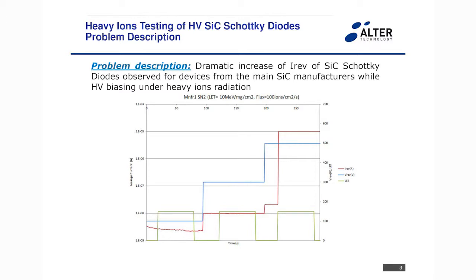This is the problem description. You have a silicon carbide high voltage diode biased in reverse under a heavy ions beam. In this case, we have an LET of 10 MeV·cm²/mg and a flux of 100 ions per square centimeter per second. In fact, the device is completely stable when it is biased at 100 volts and 300 volts in reverse. But at the very moment that the beam is activated, when the device is biased at 500 volts, you have catastrophic damage of the device, that is not a diode anymore.